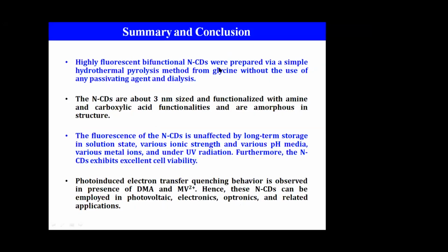So to summarize on this, we have highly fluorescent bifunctional CDs, which are really simple hydrothermal pyrolysis, synthesized from glycine as a simple organic material, and we got a size of around 3 nanometers. Fluorescence of CD is unaffected by long-term storage solution, it is quite stable, and it can have a nice photo-induced electron transfer quenching behavior with dimethyl aniline and methyl viologen. Otherwise, this material can function like an electron donor as well as an electron acceptor.